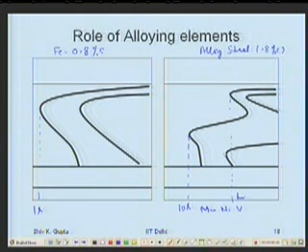This quenching, what will be the quenching? The rate of cooling has become slower. Right? Another thing, when I have so much time available to me, what I can do is, let's say my surface is cooling like this, interior is cooling like this, okay? If there's enough time for me, I can hold it for a while. So the interior and exterior both are the same temperature. And then I quench it.